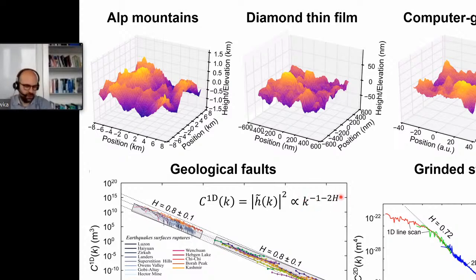So this data set here is remarkable. It's the largest continuous data set that I know of out of the group of Emily Brodsky on geological faults. And you see measurements ranging from 100 kilometers in length scale down to 0.1 millimeter. And you see that this power law scaling seems to extend over these many decades in length, and the exponent that they find is of the order of 0.8.